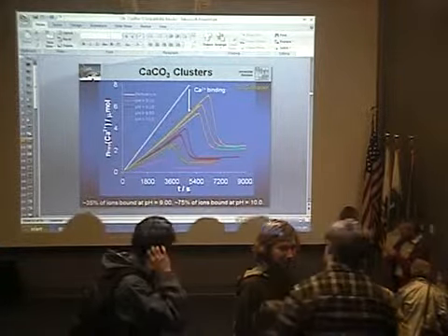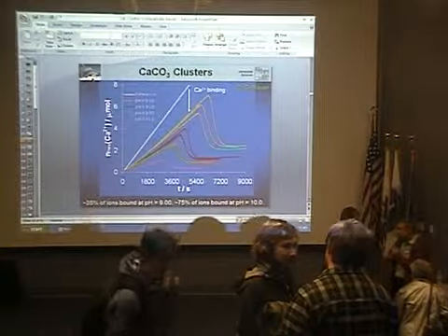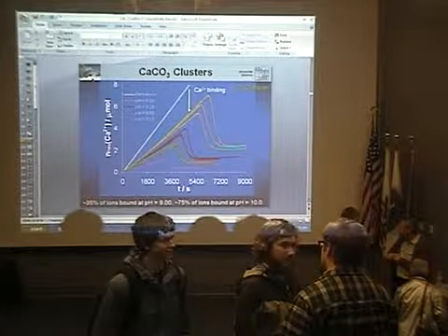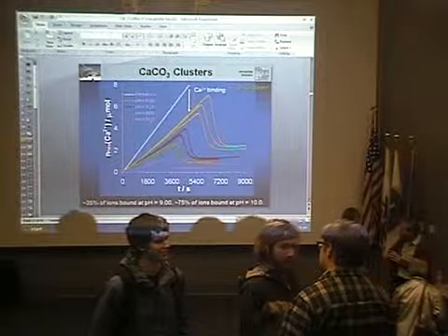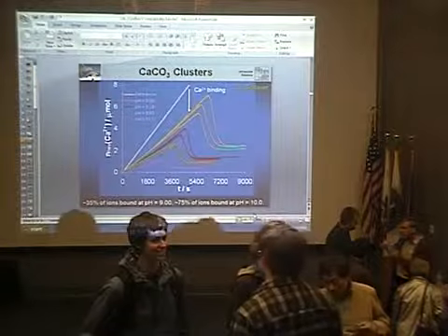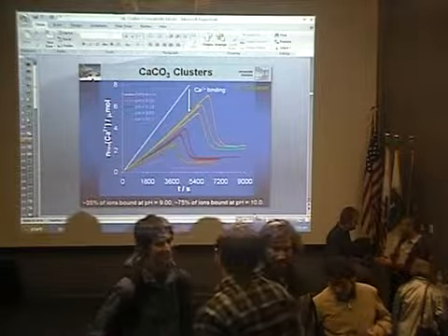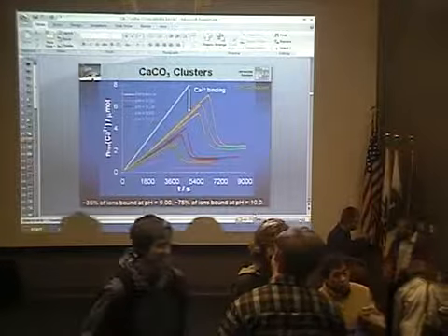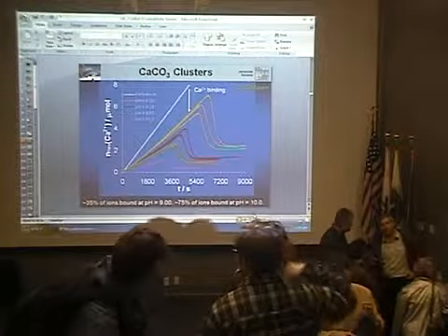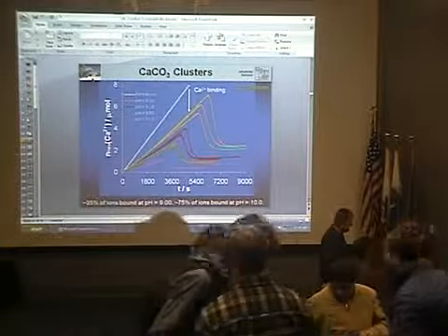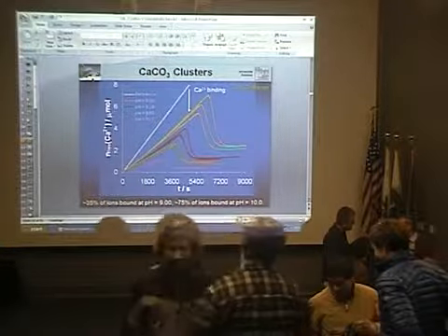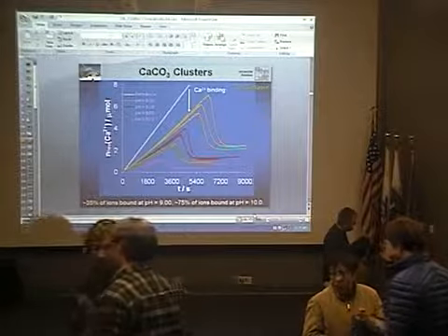Okay, so that's point number 1. The second question is, is it really a pathway through the amorphous phase? If I nucleate the crystal directly, without crossing the solubility of the amorphous phase, granted, I firmly believe that the clusters are involved because I can't explain our data without invoking some kind of magic or without invoking some kind of way to avoid adding ions on to make a big piece. But the very, very first nuclei, and we're talking about things that are sub 2 nanometers already, are crystals.